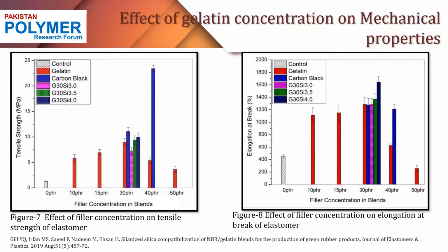The graph in this slide shows the effect of filler concentration on the elongation at break. As the concentration of gelatin increases, elongation at break increases, but on further increasing the concentration of gelatin, it reduces the elongation at break, as increasing concentration reduces the polymer rubber interaction and forms agglomerates, making the material stiffer and brittle. Because of this, elasticity reduces, and this caused the elongation at break to be reduced by a very high amount from 30 pHr to 50 pHr.